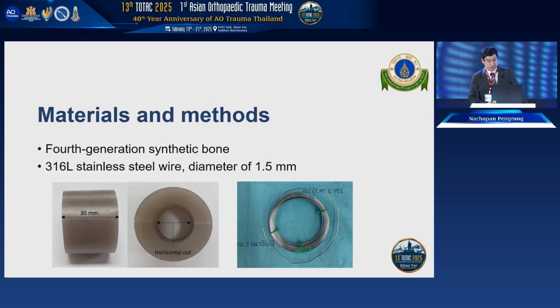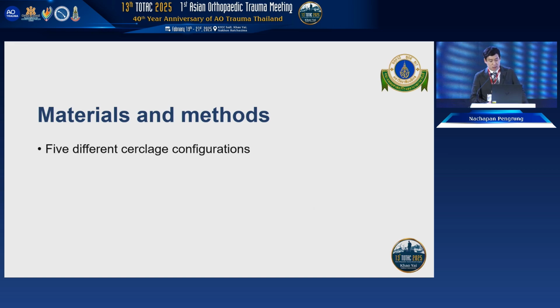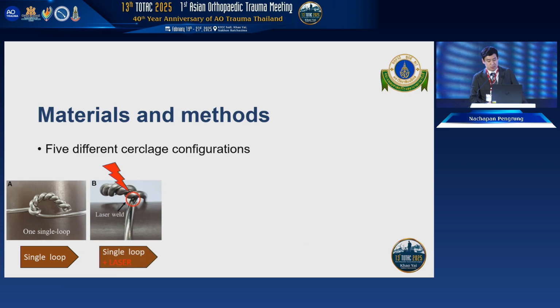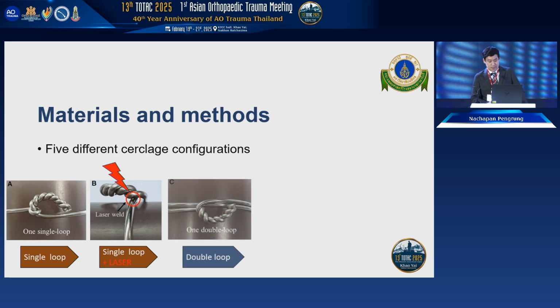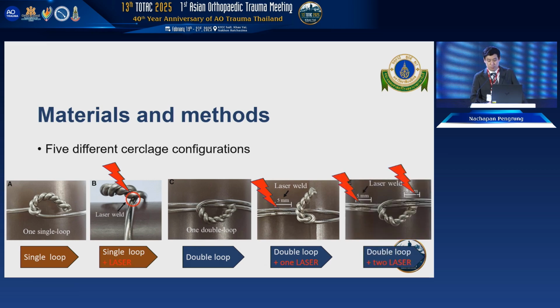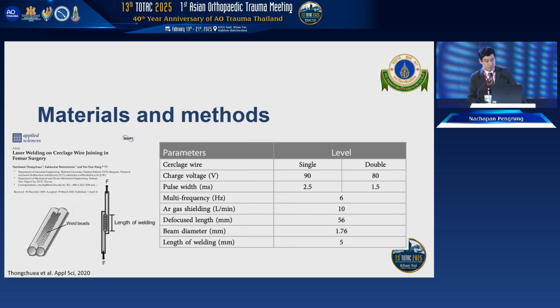For my method, we use a synthetic bone cut as in the figure, and use stainless steel wire, diameter 1.5 millimeter. We tighten it into 5 configurations. The first is the single loop. The second is single loop with laser on the spot that is connected. Another one is conventional double loop, then double loop with one side of welding, about 5 millimeter, and the last is double loop with 2 sides of welding. And we use the laser parameters as shown in the table.